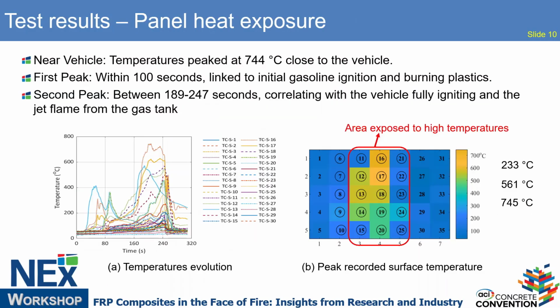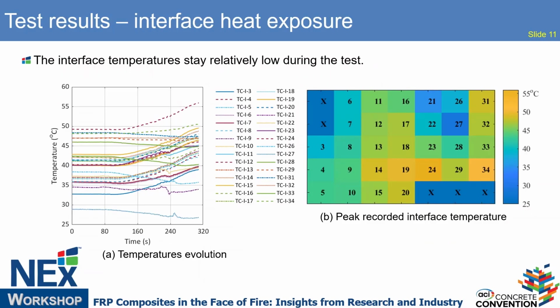So in the right plot, the area which I have circled is very close to the vehicle and is exposed to the highest temperature during the vehicle fire test. And this is the interface temperature we measured during the test, the interface between the concrete slab and the polymer concrete overlay. It's still relatively low during the test. One reason is that the overlay has relatively low thermal conductivity, which protected the interface.